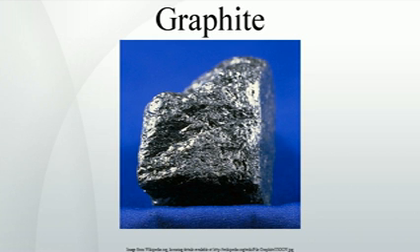This observation led to the hypothesis that the lubrication is due to the presence of fluids between the layers, such as air and water, which are naturally adsorbed from the environment. This hypothesis has been refuted by studies showing that air and water are not adsorbed. Recent studies suggest that an effect called superlubricity can also account for graphite's lubricating properties.